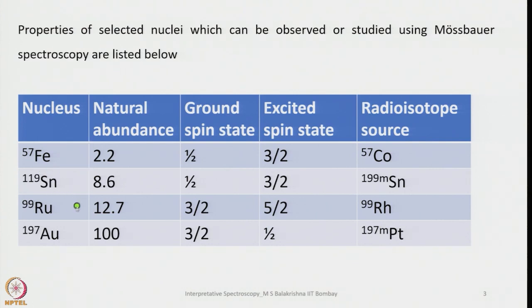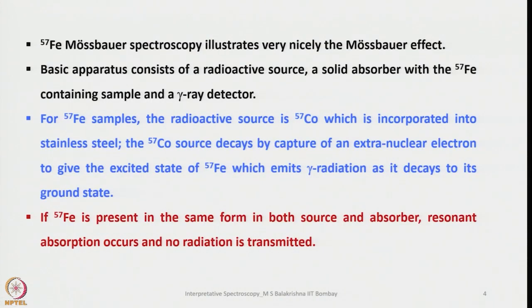57 iron, 119 tin, 99 ruthenium, 197 gold, and natural abundance is 2.2, 8.6, 12.7 and 100, and ground spin state is 1/2, 1/2, 3/2, 3/2, and excited spin states are 3/2, 3/2, 5/2 and 1/2, and radioisotope source we used in case of 57 iron is 57 cobalt, in case of tin is metastable 119 tin, and 99 rhodium, and then in case of 197 gold, it is 197 metastable platinum. And here, if you want to illustrate Mössbauer effect, 57 iron Mössbauer spectroscopy comes very handy to illustrate very nicely the Mössbauer effect.